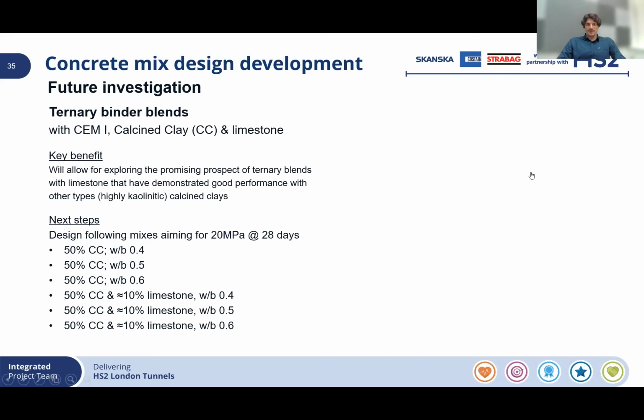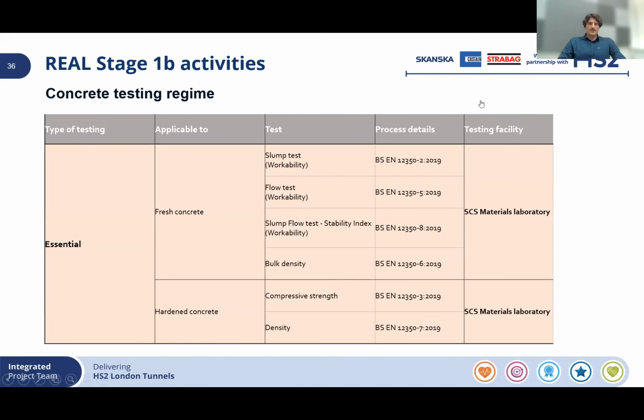As a secondary possibility that is probably going to be investigated in the future, we are also investigating ternary binder blends like the LC3 type of blend, where we combine calcined clay, limestone, and Portland cement, again, to see how the synergistic effect of limestone works with calcined London clay, and what kind of strengths we can achieve. Again, our target strength is the same as before, targeting the low strength applications, which are also the lowest in risk, considering that they don't contain any reinforcing steel in the project.